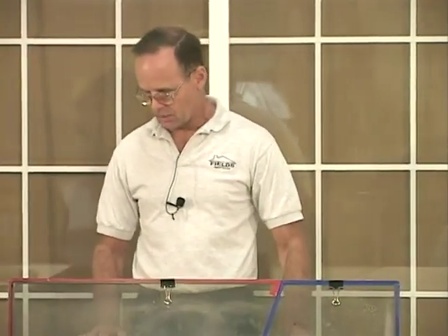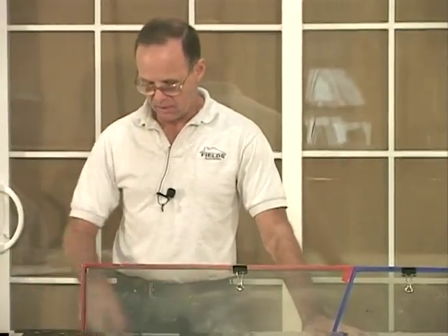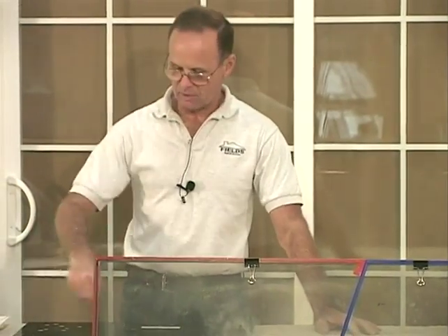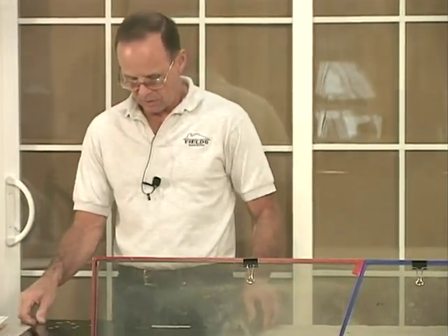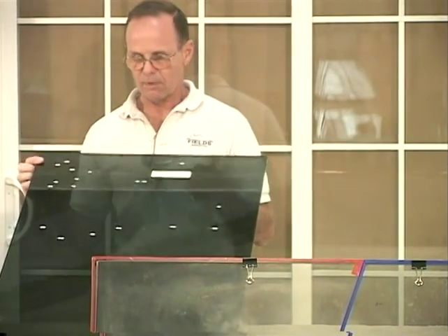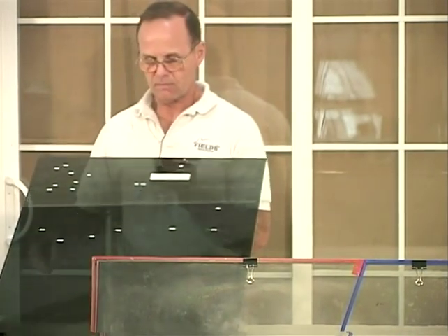And they show up a lot more on pyrolytic coatings. But some tin etch haze shows up a lot more than others. This one here I actually did, and I wrote "tin side" with a sponge with the hydrofluoric acid. And I'm sure it's not going to show here, but it's along the top. But we will see some in our images.